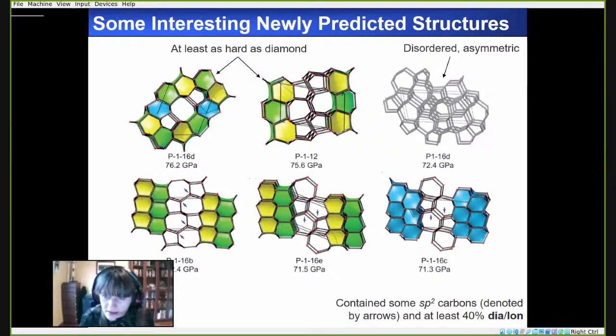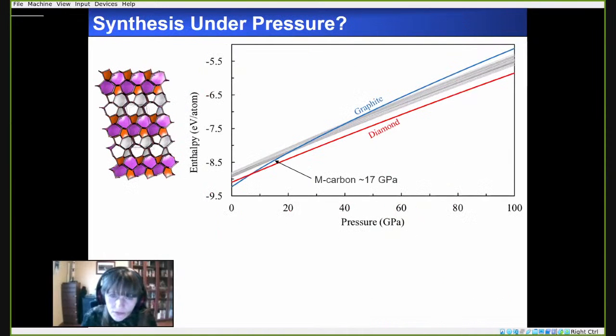However, we note that this system here was not. It had a very low symmetry and it was disordered and asymmetric, and it has been proposed that also low symmetry could give rise to very hard materials. So could some of these be synthesized under pressure?